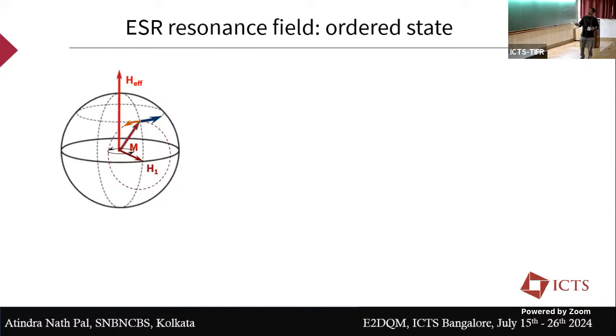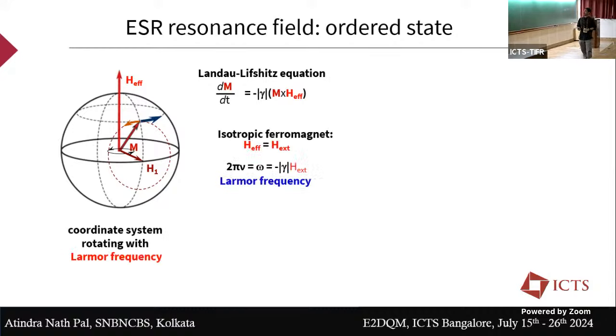If you apply a magnetic field in the case of an ordered state, what will happen? The magnetization will start precessing, following the Landau-Lifshitz equation. For an isotropic ferromagnet, if you don't have any kind of anisotropy, H external is nothing but the effective magnetic field, and the resonance condition will be that the Larmor frequency equals gamma times H external.